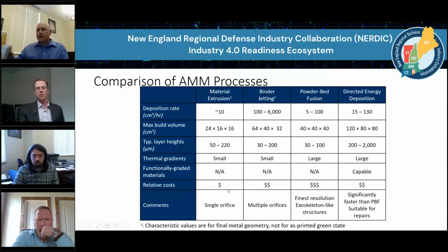Material extrusion is really one of the least expensive ways to get into additive manufacturing of metals. Powderbed fusion is typically more expensive, and you can get finer control. Powderbed fusion is more common in aerospace and biomedical. As metal additive manufacturing gets more closely aligned with traditional industrial processes, material extrusion and, at high volume, probably binder jetting are going to be more dominant, with directed energy deposition definitely playing a role with enhanced functionality and anything to do with repairs.